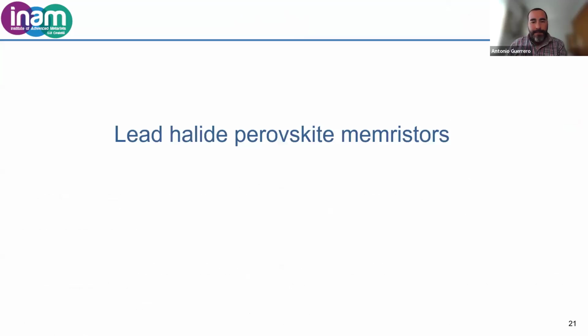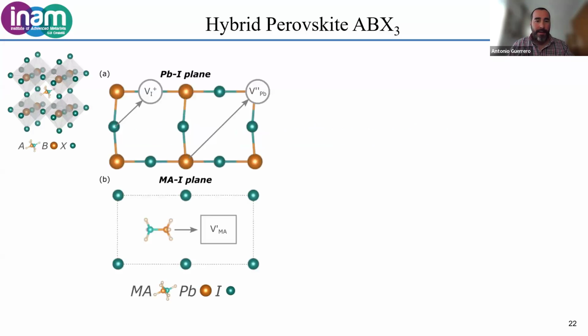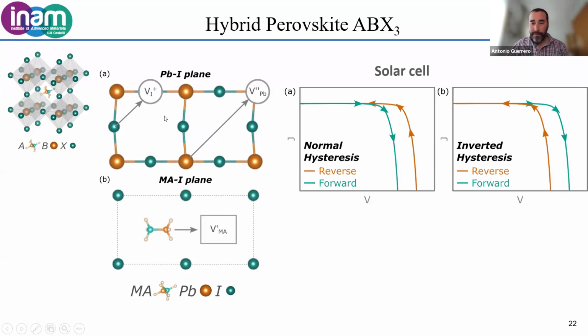So let me move on to lead halide perovskite. I have introduced ion migration and hysteresis in the solar cell. In the perovskite, as I mentioned, it is the iodide in the crystalline structure which is responsible for the main response in the hysteresis, because the halide can migrate. And this will give a different type of hysteresis depending on the configuration of the solar cell. So this is the case where we call normal hysteresis: the forward scan gives a lower current than the backward, than the reverse. And this is what is called inverted hysteresis, where the forward gives a higher current than the reverse scan.